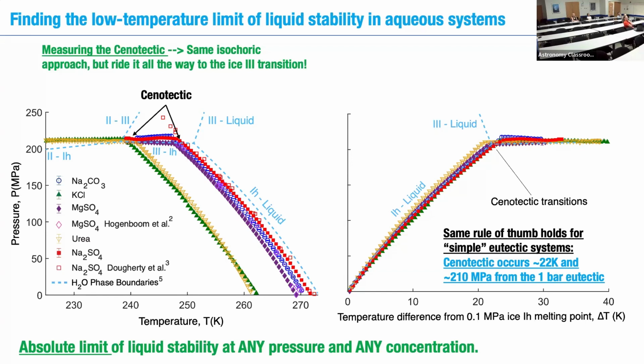Okay, so we've solidified this rule of thumb that for simple eutectic systems, and I'm defining simple here as things that don't have a bunch of other phases between the eutectic and the solid solute phase, the cenotectic will generally occur at the same place that the triple point occurs for water and ice, right? Where that denser ice transition happens. So this is generally about 22 degrees Kelvin below the atmospheric pressure eutectic temperature, and 210 MPa. Okay, so this is the rule of thumb that we're now applying to simple eutectic salt systems.